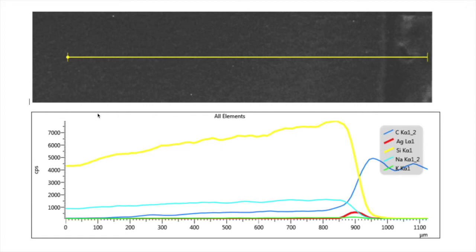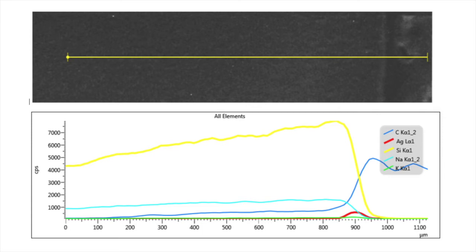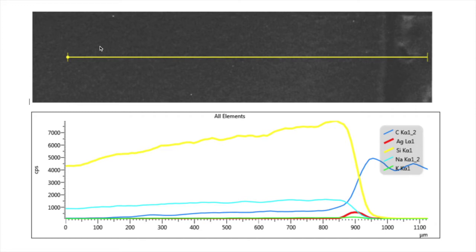Next, this is an example of a line scan. Just as a reference point, this is actually collected from MSE 407, as part of a glass lab. It's an inorganic glass rod and it's been exchanged. The potassium ions in the glass have been exchanged for silver ions in a molten bath. The top part here is a kind of a fuzzy quality SEM image. And then this yellow line is the line scan that we're scanning across.